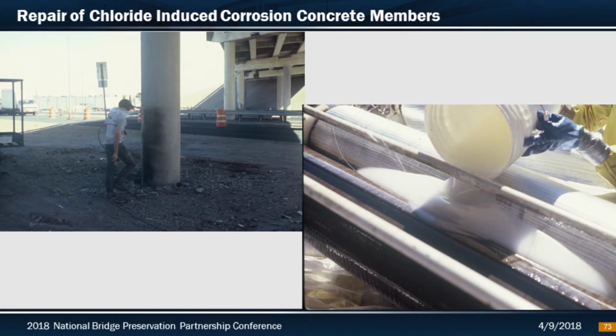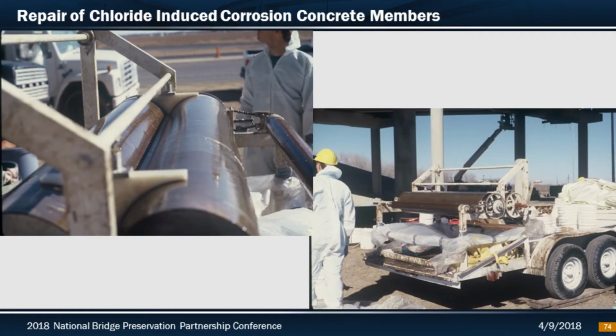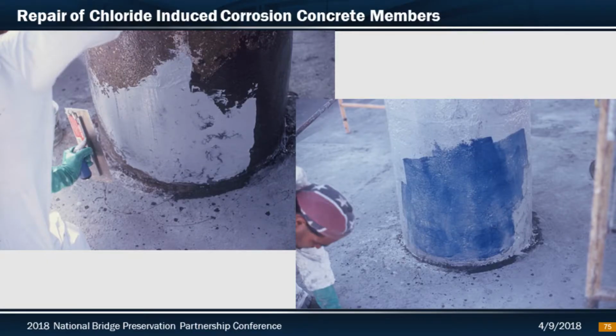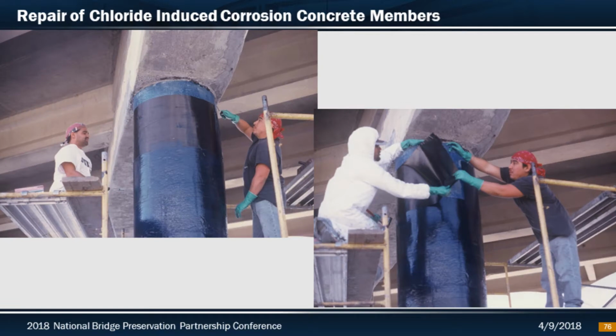Prior to the wrapping, we sprayed a corrosion inhibitor onto the columns and the vent caps. And then again, this is a wet layup saturator that was used for the resins on the glass fiber. These were UV resistant resins used on that glass fiber, thoroughly saturating to wet out the fiberglass and get a good bond and a good matrix. The primer's applied.